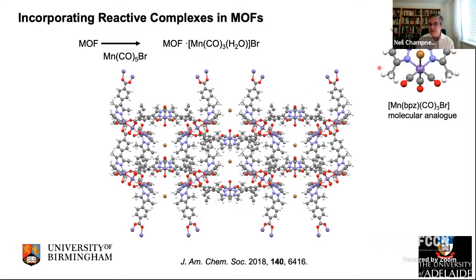And you can see over here, this is kind of a model complex. This is the molecular species of what you normally anticipate. And in the MOF, you see something slightly different. What you see in the MOF is that you actually end up with a water ligand bound to the manganese center and the bromide sitting as a counteranion. This is just because in our process, we have a little bit of water around in the ethanolic solution of the manganese pentacarbonyl bromide. And it turns out the solvent's important in this process.